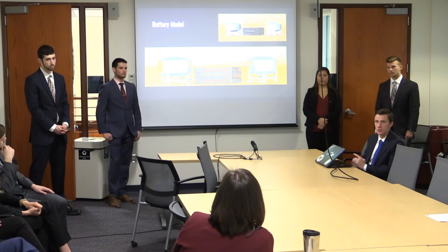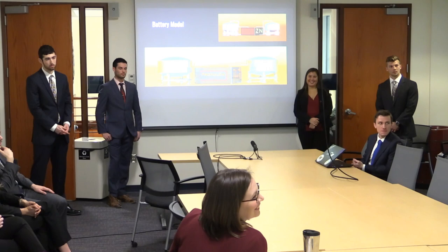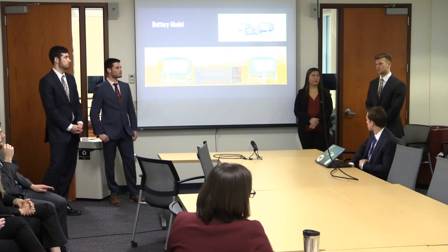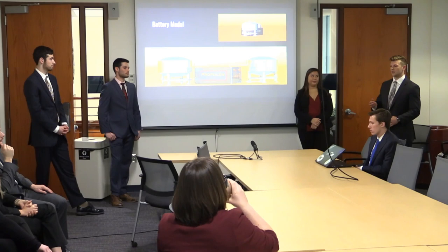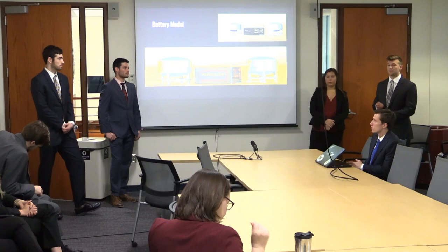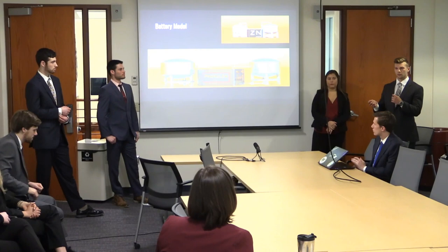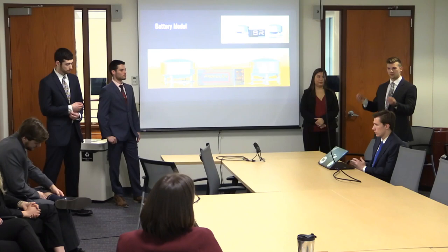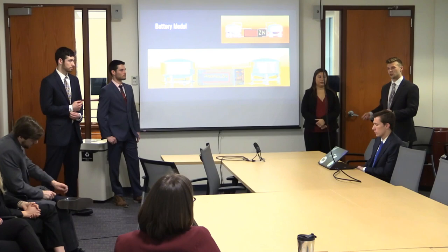The refinement of zinc and bromine requires a lot less energy and lower temperatures than iron, chromium, or titanium, making it more reasonable for production on Mars. Did you use your experimental energy density values for the scale-up design? That was not something we were able to gather experimentally, because cells in the field are run at 2.5 molar concentration — a higher concentration than we could test. At higher concentrations, we got more zinc dendrite formation on the rotating electrode, which created increased area and increased reaction rate, muddying our data. So we used a lower concentration during experimentation, not necessarily representative of the power on an actual system.